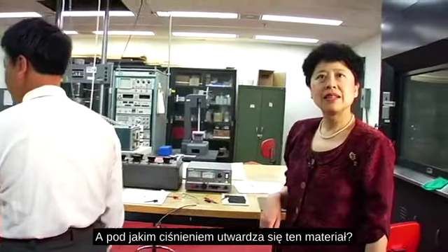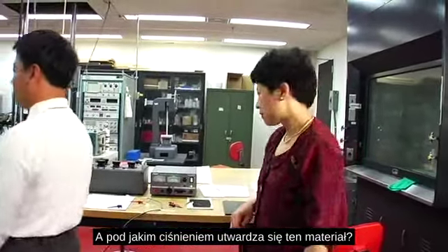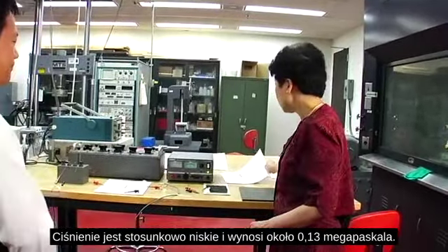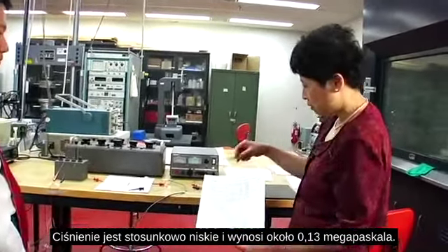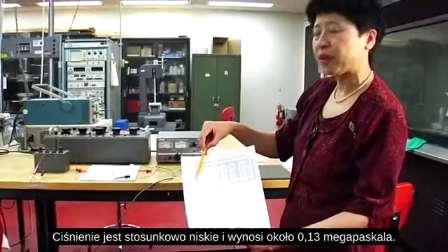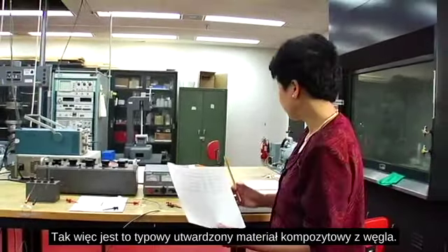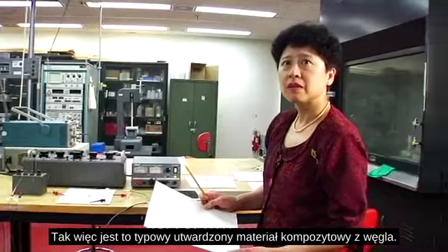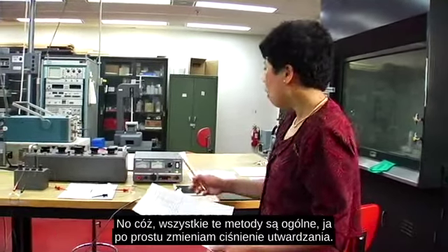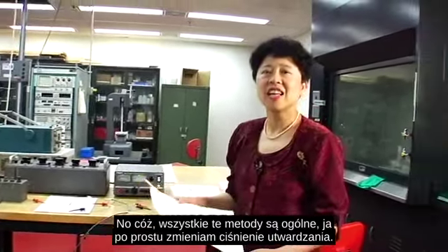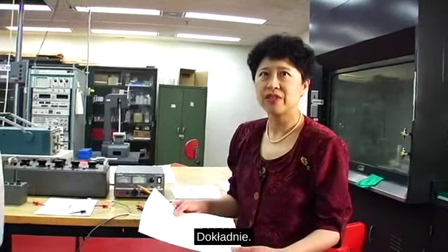And this is with material that has been cured at what pressure? The relatively low pressure, which is around this 0.13 megapascal area. So this is generic carbon composite cured material. Well, all these are generic, except that I vary the curing pressure. Exactly.